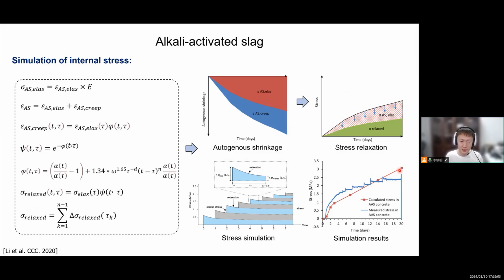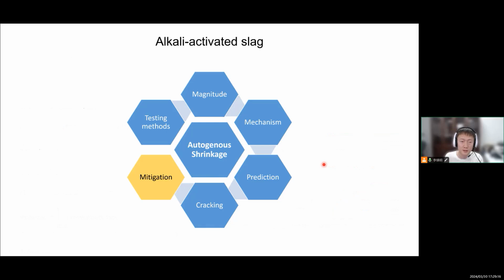And if we know the flexural or tensile strength, we can compare stress with strength, then we should be able to roughly predict the cracking time, which is really useful for the structure analysis. Since we know that there is a large shrinkage and also the cracking still occurred, although it is not so early, in the 2 or 3 days, it still occurred within 3 weeks, which also means very high cracking proneness. Then we need to find some solutions to mitigate the shrinkage and the cracking proneness, of course.